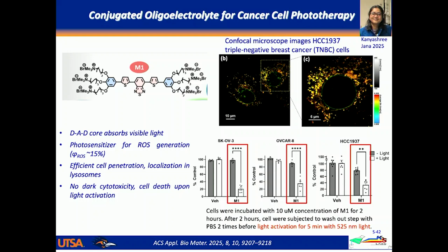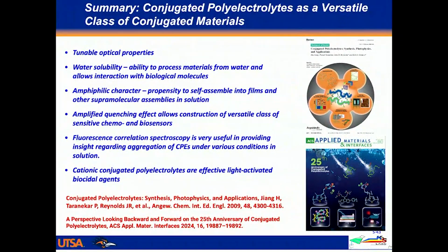We don't exactly know the mechanism. It turns out this molecule is not a super efficient singlet oxygen generator. It's got a pretty low energy triplet state, but we do believe that it is generating some sort of reactive oxygen, either singlet oxygen or perhaps oxygen type radicals through a type 1 mechanism. But nonetheless, it is able to kill the cells with light exposure. So I think I'll stop there.